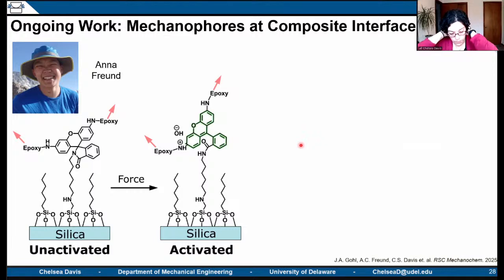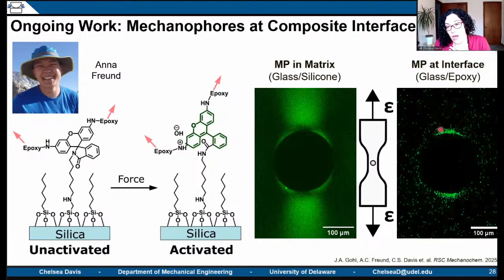Others have published several explorations of these, mostly looking at particles that are functionalized with a mechanophore that have some sort of polymer tether that entangles into the polymer network or into a solution or a suspension of these nanoparticles. And those have already been demonstrated. Others have figured out how to do this chemistry. What we were excited about was this initial proof of concept that we can get interfacial activation at the interface in a thermoset matrix cured around a rigid inclusion.